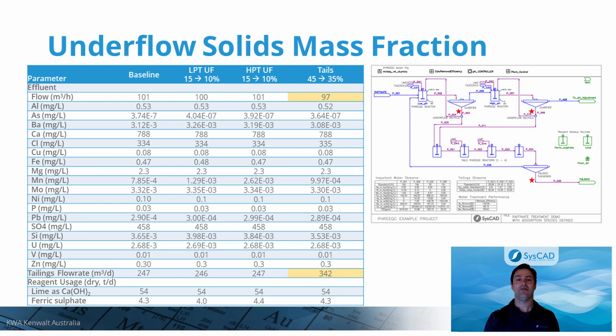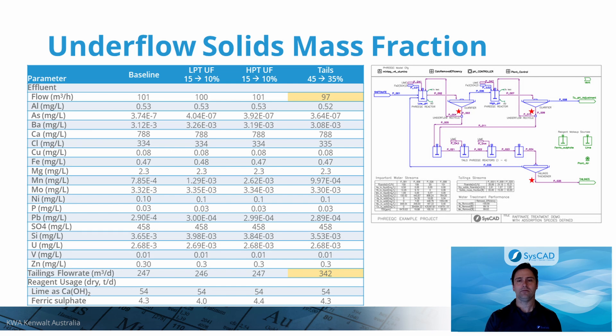In this slide, the effect of varying the underflow solids composition for each of the clarifiers and thickeners on final effluent is predicted. The low and high pH clarifiers affect internal streams to the process, but they don't have any effect on the final effluent, as seen in the second and third columns. The far right column indicates that changes in the run-of-mine tailings solids content has a significant effect on effluent flow volume. The effect on concentrations is minimal in all cases.